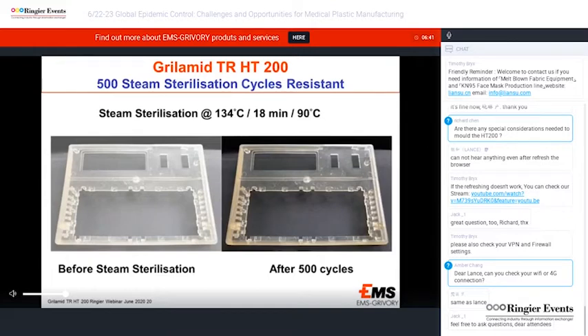Also, in regards to the color, we do not see a significant change after 500 cycles. On the left-hand side, we have a photo of before sterilization. Here we can see that it has a slight yellow tinge to it, which is inherent to polyamides. This, however, can be compensated by adding a blue master batch, which basically neutralizes the yellowness and allows a neutral or water-clear solution. On the right-hand side, we have a photo of after 500 cycles. Here we can see that the yellowness has slightly increased, but the TR HT 200 is still fully transparent without any sign of haziness or distortion.